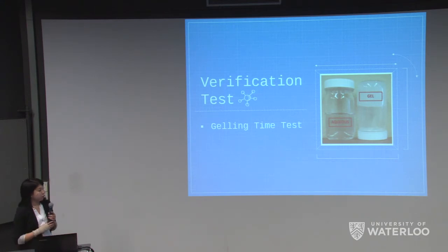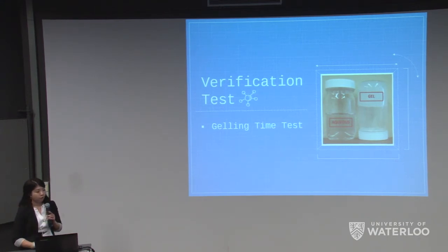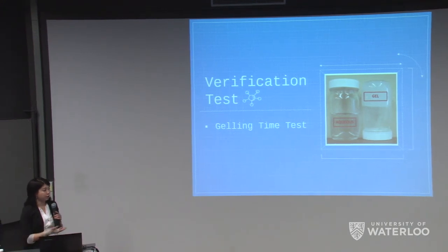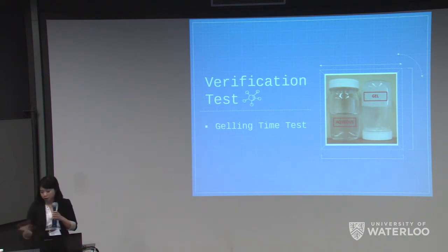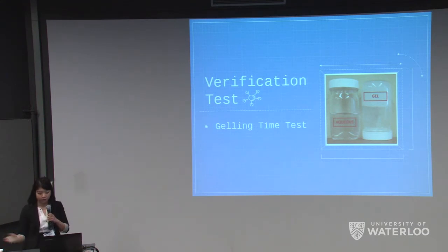To ensure the positive thixotropic property of our electrolyte, first the gelling time needs to fulfill the manufacturing requirement, as Skylar mentioned earlier, of 4 to 24 hours of gelling time within the AGM separator before it solidifies. And to get an idea of the effect of the thixotropic effect, as you can see on here, these are our 2 vials that we demonstrated earlier, the aqueous and the gel electrolyte.